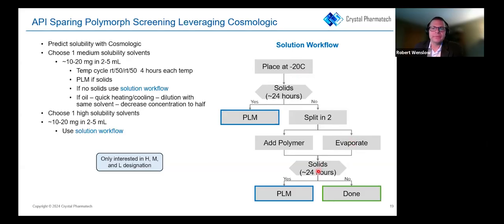And then again, PLM, just get a quick microscope image. If it's crystalline, then get an X-ray. You don't have to go immediately with the X-ray. And also take into consideration the solvents. This is where you use COSMOlogic, so I don't have to waste 0.5 gram of material getting estimated solubility. I get one accurate solubility, ideally a water solubility, or ideally a FaSSIF solubility. Then I go into COSMOlogic and say, okay, what's my approximate solubility in these solvents going to be?